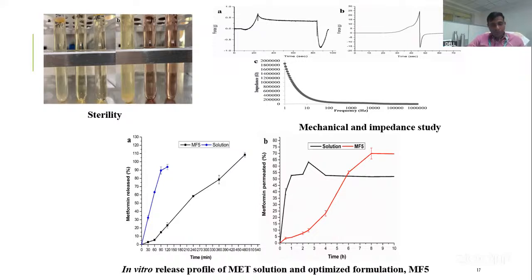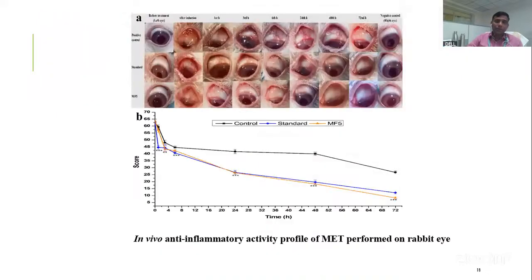And we have performed the drug release profile of the metformin solution. The solution released the drug within almost 1.5 hours, whereas the polymer-containing metformin in situ gel released the drug over almost 8 hours. Further, we have performed the in vivo anti-inflammatory activity of metformin